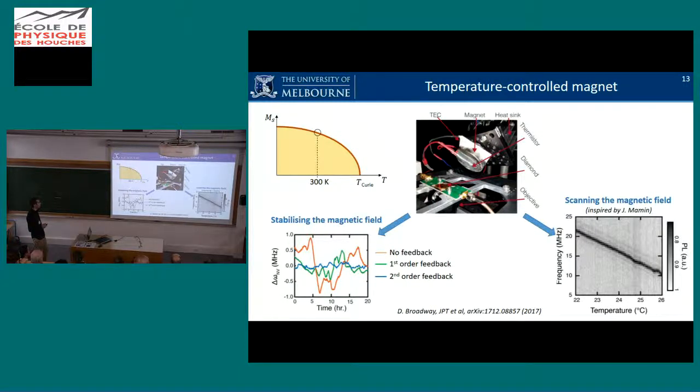It's very simple; the temperature dependence at room temperature is roughly linear. If you just scan the temperature, for instance here by 4 degrees, you shift the frequency of the NV by up to 10 megahertz near the GSLAC. You could imagine having an even wider scanning range, and that's sufficient for most NMR and EPR spectroscopy that you can do with cross-relaxation.